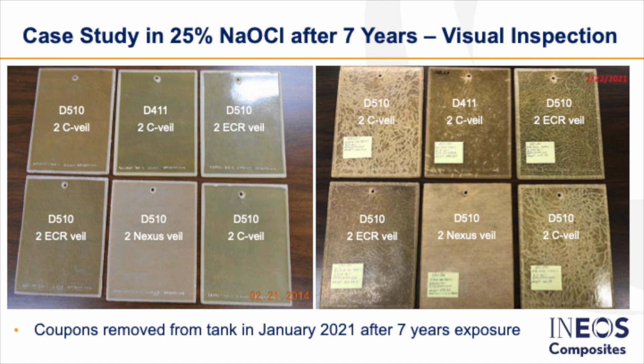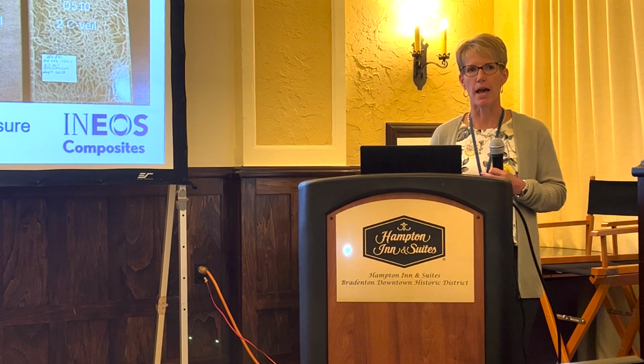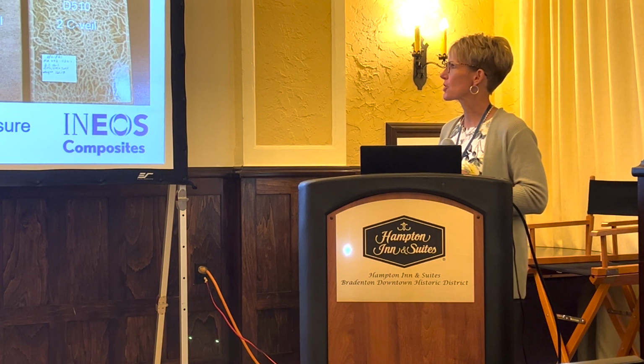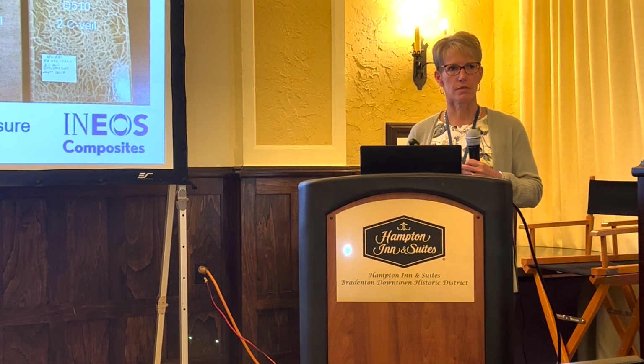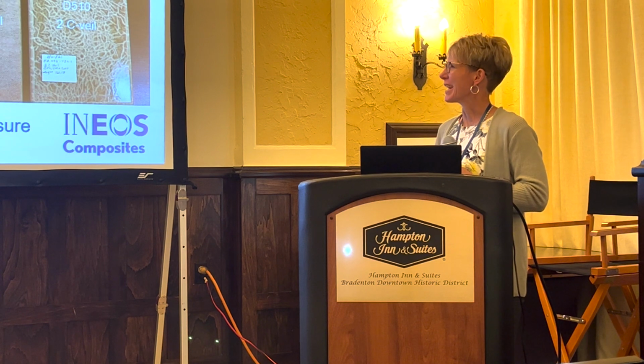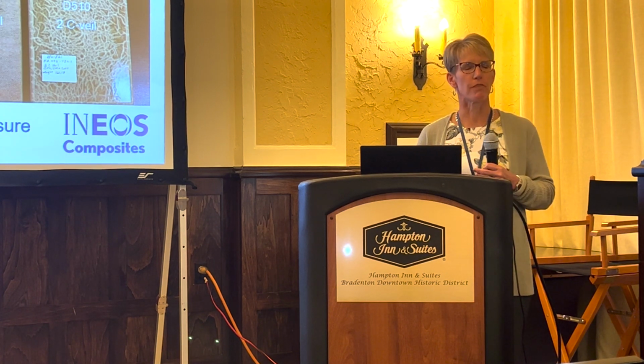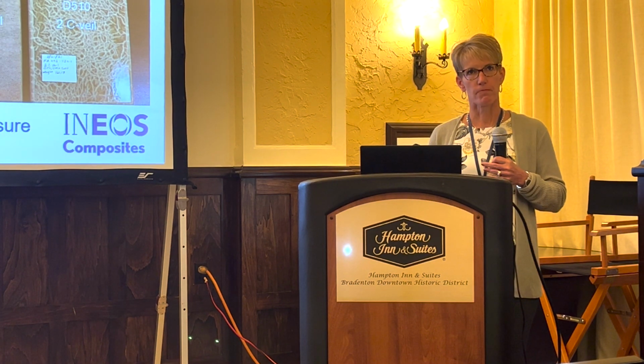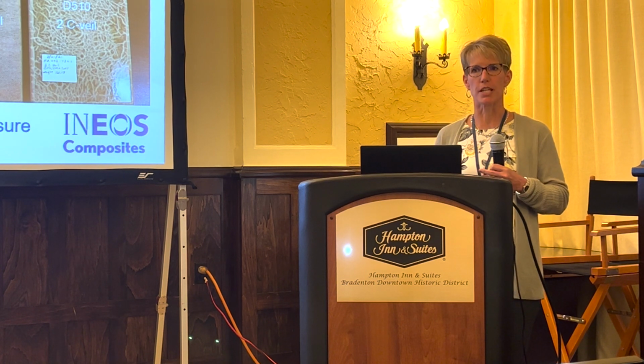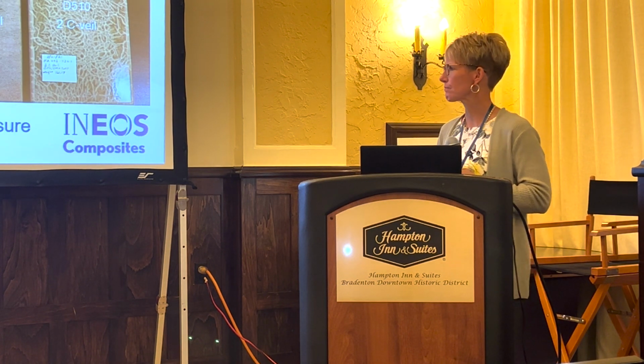This is a case study where we were able to send coupons to a customer. They immersed them in 25% sodium hypochlorite at their facility, and after 7 years, we were able to get those coupons back and do a visual inspection and also some flex testing. As I mentioned in the beginning, this is going to provide you with a little bit more detailed data because you're actually immersing them in a process.